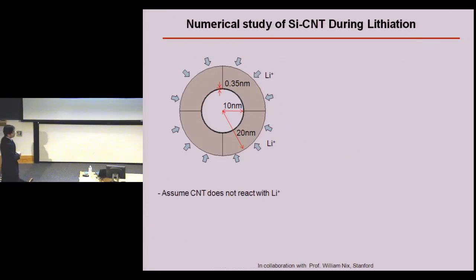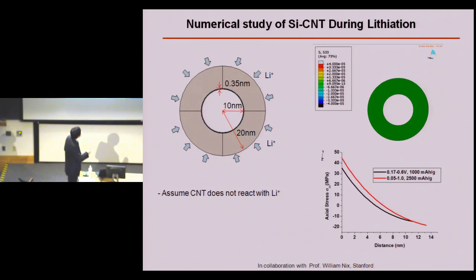And together with Professor Nix's group at Stanford University, we started to do some simulation to understand the stress distribution for this kind of structure. This is the carbon nanotubes. This is the silicon coating on the surface. And this is the stress distribution along this line. So this is zero here. And as we move away, we see the stress decrease. So there's a huge stress building up at the interface between nanotubes and the silicon during the lithiation process.